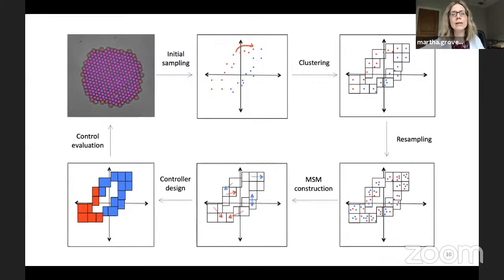But once we've resampled, now we can figure out how the system evolves under each action over a fixed time step. And there we construct a Markov state model that just really describes the probabilities of moving between the discrete states under each action. And that model provides the input into our calculation of our optimal policy, which is shown then on the lower left, and just constitutes a lookup table. So we take a measurement, and if we, at that point in time, are in a blue box, then we take, say, the low temperature action in the next time step. If we're in a red box, then we do the high temperature. And then we actually test out the policy in the experiment. And often we go around again because we've actually found some new states. So there's actually another feedback loop around this cycle a few times.